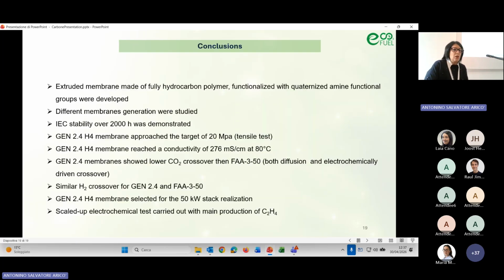So, in conclusion, in this work package, extruded membranes made of fully hydrocarbon polymers based on quaternary ammonium functional groups were developed and scaled up, with good stability in terms of anion exchange capacity, very close to the target of 20 megapascal considering the tensile strength, good conductivity of 276 millisiemens per centimeter at 80 degrees, and lower CO2 crossover, and also scaled up for the 50 kilowatt test.